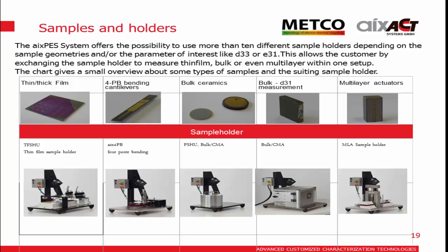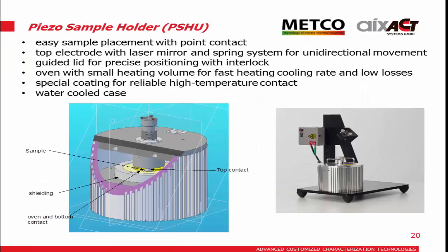For the evaluation, this is the sample holder for bulk materials. It has a very small heating volume, and the sample can be easily placed inside, establishing the point contact to the sample from the top and the bottom. We measure on the top by a single beam laser interferometer on the top surface by a rod, basically, which has no big force, so that we are independent of the electrode materials. For example, silver paste or degradation of the electrodes or planarity does not have a big effect here. It's mainly a matter of precise sample placement, and can also maintain a fast heating and cooling rate to speed up the test in this setup.